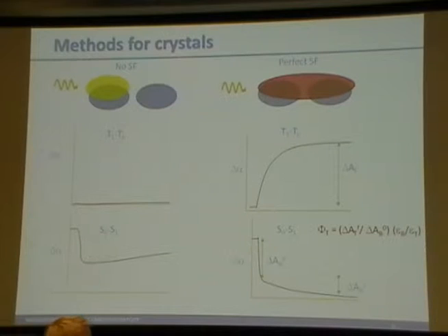One additional way of detecting the influence of singlet fission is this secondary rise that I mentioned. And if you measure the amplitude of the bleach of that secondary rise and compare it to the initial rise, that's also a measure. So let's say it increased 50% from where it was initially. That would mean that 50% of these molecules underwent singlet fission. Again, you'd get 150% yield.